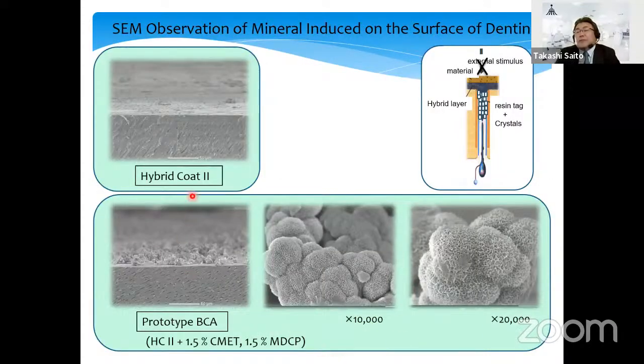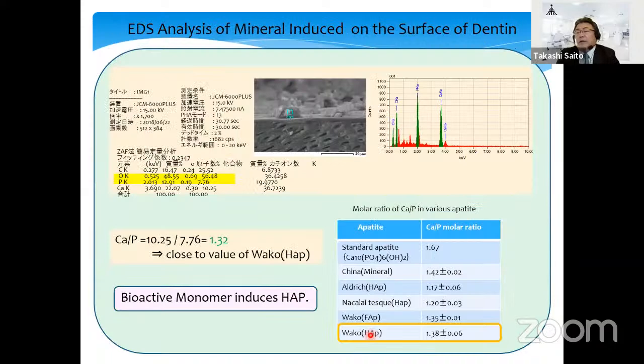Both Hybrid Coat 2 and the prototype BCA sealed dentinal tubules in the SEM. We can observe some precipitation on the surface of dentin coated by prototype BCA. The precipitation was an aggregation of spherical crystals. We performed an EDS analysis of mineral crystals induced by prototype BCA on the dentin surface. The Ca/P molar ratio of the crystals was 1.32, close to the value of Wako standard hydroxyapatite. So the bioactive monomer induced hydroxyapatite.